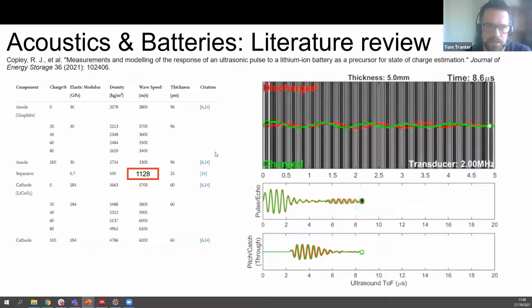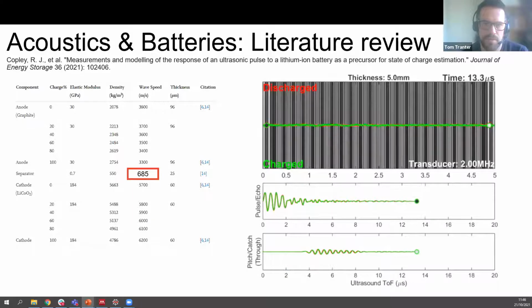And if you compare this signal with that signal, you can see that you've halved the wave speed just on this very small layer, and you've completely changed the signal response. And there's a little bit of tuning, I guess, that has to go on in terms of the frequency. Using the same acoustic setup for different cells is not always going to necessarily be the case to provide you with good signals. I guess it's taking a message from this particular figure or image.